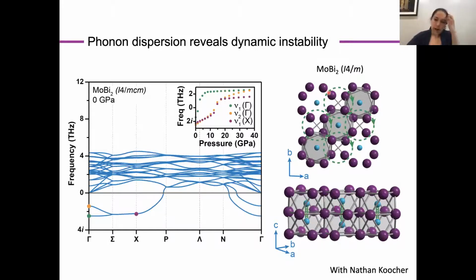However, also notably, we notice that molybdenum is also moving in response to the decompression. We are creating a Peierls type of distortion in our chains of molybdenum, which were initially at high pressure equally spaced, but by the time we get to this polymorph, we now have alternating long and short distances, both along the z-axis, as you might expect, but also in this direction as well. All of which is to say that we have identified a new molybdenum bismuth intermetallic that, of course, I didn't find in my thermodynamic exploration of this phase space, but we predict belongs on the convex hull. We do predict that it corresponds to a local minimum, and therefore is a really promising potential target if we can carefully control the amount of kinetic energy we introduce to the system as we decompress it, for isolating a sample of molybdenum bismuth 1-2.